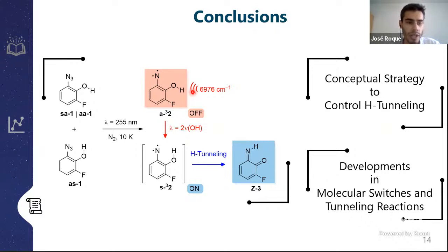Yeah, the conditions are perhaps the main advantages. The disadvantages are that, of course, we are working at 10 Kelvin. So when we try to increase the temperature, which should be our aim in the future, these rotations of conformers will stop being hindered. They will just occur spontaneously. So we'll somehow stop having control over it. And in terms of the amount for our experiments, the way we prepare these samples is that we sublimate our sample slowly, and the bands start increasing over time, and when we have absorbance close to 1 or 0.8, we close all our valves and stop depositing the sample. So in that sense, we have some control over the amount that we are preparing.